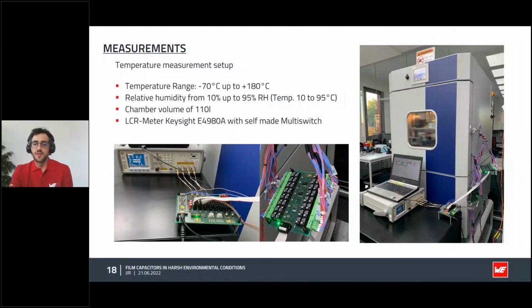I want to show you the measurement setup for this kind of test. This is one of our climatic chambers in our office in Berlin. It's a very versatile and powerful chamber. The cabinet volume is 110 liters, and the temperature range is from -70 to 180 degrees, with a maximum humidity of 95%. To multiply the measurement possibilities of our calibrated LCR meter, I designed and programmed the modular multi-switch system that you can see in the image. I can control it as a USB device and switch between several DUTs, thanks to the relay boards that you can see in the middle picture.